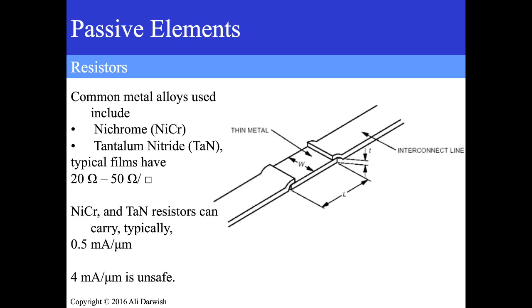For the thin film resistors, as I said, we typically have two types of materials that get deposited, either nichrome or tantalum nitride. And the foundry would design the resistance per square to be 20 or 50 ohms. But one thing to notice is, what is the current limit for the resistors? It's about half a milliamp per micron. And so if we have the width equal to, say, 10 microns for the resistor, then we're able to handle 5 milliamps across it. Sometimes people may mistakenly say, well, I'm not passing any DC through it, I'm just passing RF through it. Well, the RF also has a root mean square value. So the RMS value of the current at the resistor is going to result in heat, and that heat is going to damage it if it exceeds the safe limit.